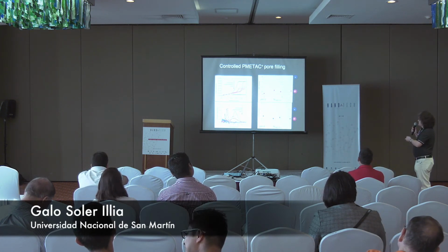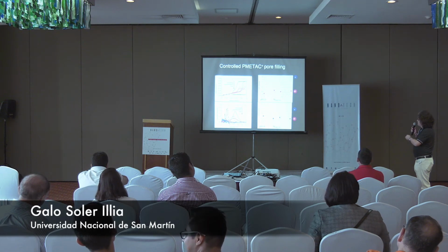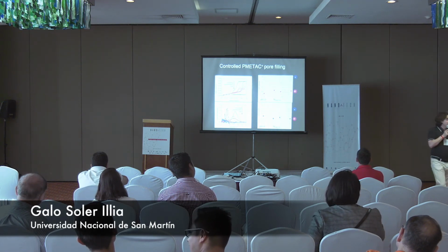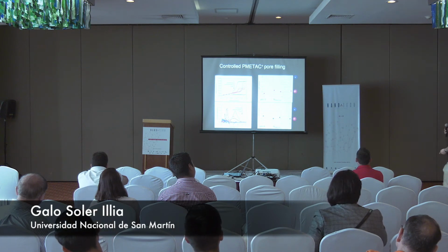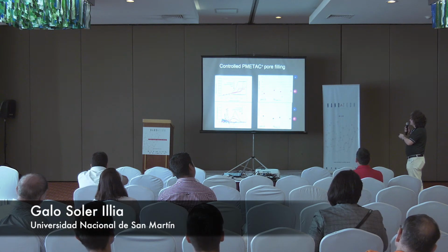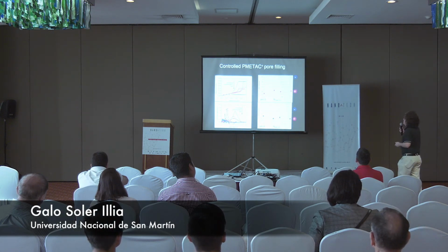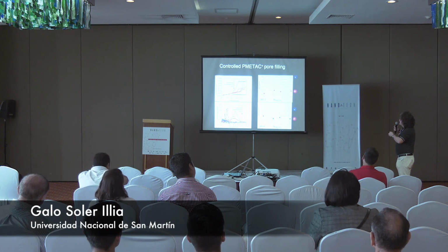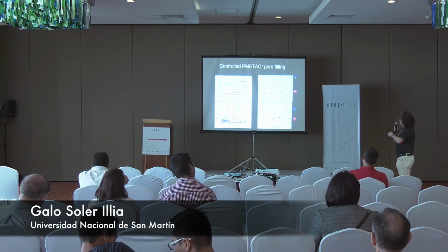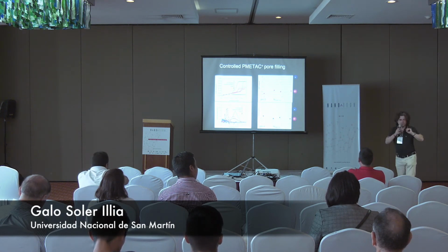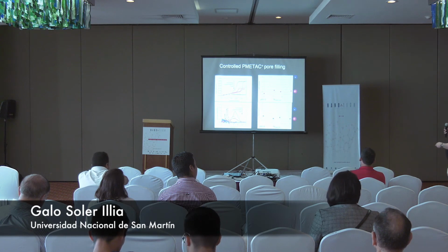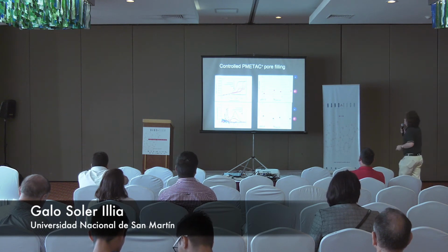And we observed that, for example, this is the signal of positively and negatively charged molecules crossing or not the membrane. This is when we increase the size of the polymer. For small polymers, a positive or negatively charged molecule can go inside, but when we increase the polymer size, a negatively charged molecule is pre-concentrated while the positively charged one is not passing. It is passing a little bit, you will see, but not passing. And this effect can be retrieved and is very reproducible.